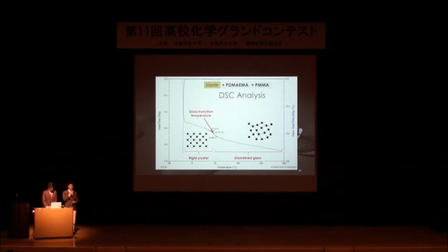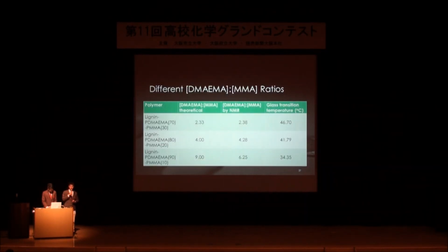In order to determine the glass transition temperature of our polymer, we perform the DSC. So what is the glass transition temperature? It is the temperature whereby our polymer transforms from a rigid crystal structure as shown here into a disordered glass structure as shown here. So the glass transition temperature basically measures indirectly the hardness or softness of our polymer.